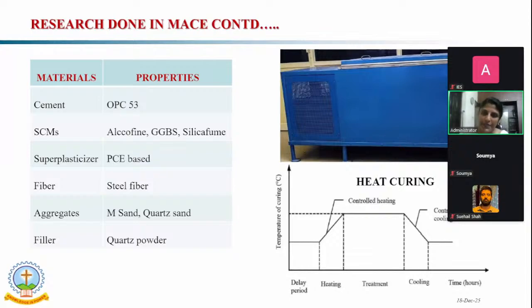Then also the curing period. That means in the accelerated curing tank, we kept all the specimens for 24 hours, 48 hours, and 72 hours. From all the research, we agreed that the 48 hours curing period gave the best results. How we put in the heat curing is that the accelerated curing tank has 2 layers. In the first layer, we kept the water and heated that water to 90 degrees centigrade for 48 hours. In the second layer, we put the specimens for 48 hours.